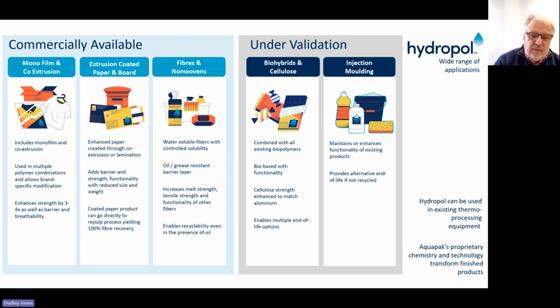With fibre and non-wovens, with our resin, we can create a thread that is then woven, and a sheet is soluble. Under validation in development, we have a combination of biohybrids and cellulose. So we're looking at our material with different materials, specifically cellulose. Our foundation work and development work in R&D has shown that this is an area that is very interesting, and we move forward in this once we realise that the strength will match aluminium. So very unique materials being created, and then also injection moulding. You can see that we are working in different areas, but today we have three commercially available routes for product.